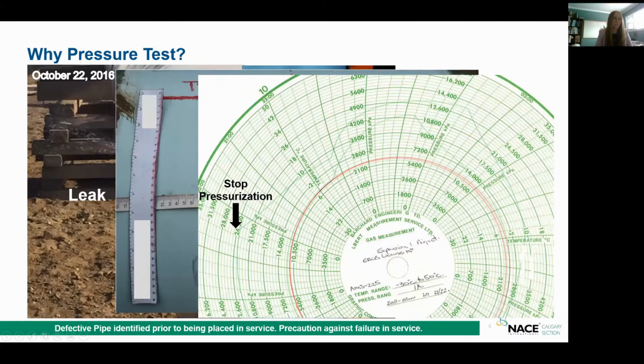So the field finally decided to stop pressurization. And you can see that it immediately was experiencing a drop in pressure. And so realistically, there are lots of signs, as you're getting that curved approach, that there's an issue and that the pipe is either deforming or unable to contain pressure. So this is another example of why it is so important to have experienced and competent people at site overseeing the testing of your pipeline.